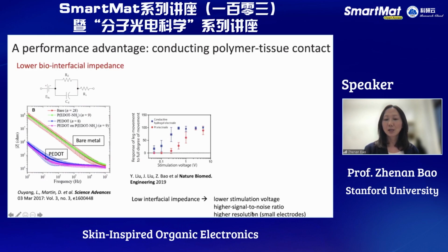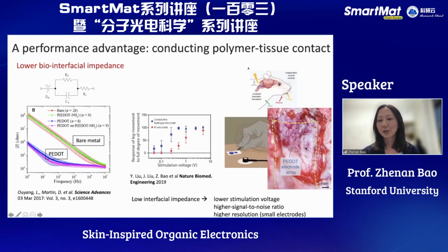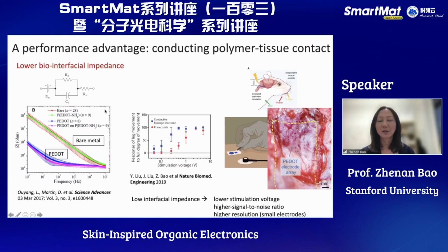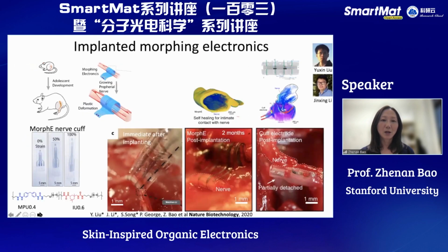And the other implication is a higher signal to noise ratio. That means when we try to measure these electrical signals to do mapping either on the brain or on the heart, on the muscle, with a higher signal to noise ratio, we can reduce the size of the electrode and have really high resolution mapping, while standard ionic gels require a large area. And because it only has the capacitive term, it has a very high resistance, but having both the conductivity and the high capacitive term, then we can really start to achieve high resolution mapping.